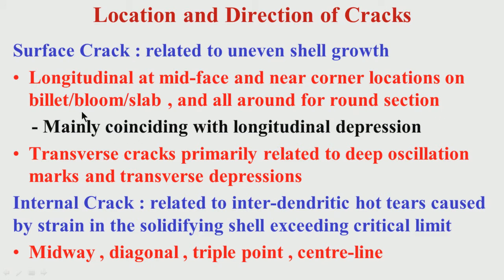Now, these longitudinal cracks sometimes or most of the time coincide with the longitudinal depression. I have told you there is a possibility of longitudinal depression in depression grades because of uneven shell formation. So, if you have longitudinal depression, normally you find beneath those depressions there will be cracks. So, longitudinal cracks can coincide with longitudinal depression.